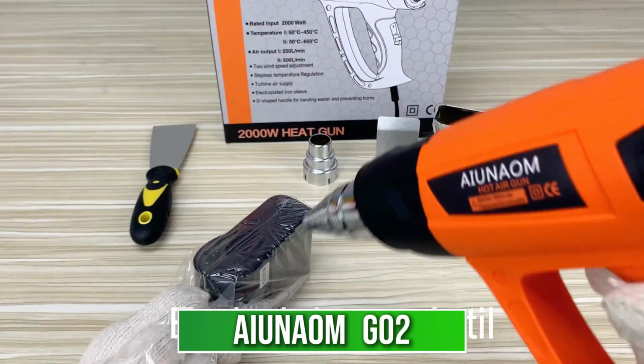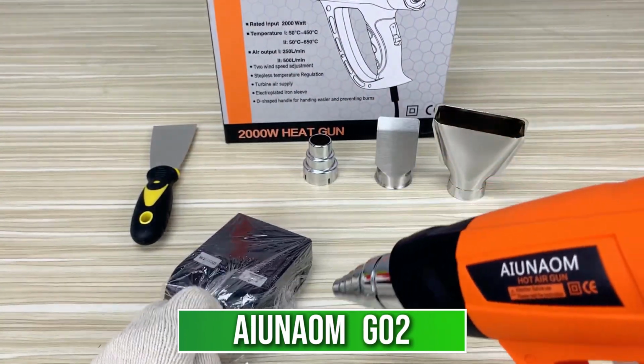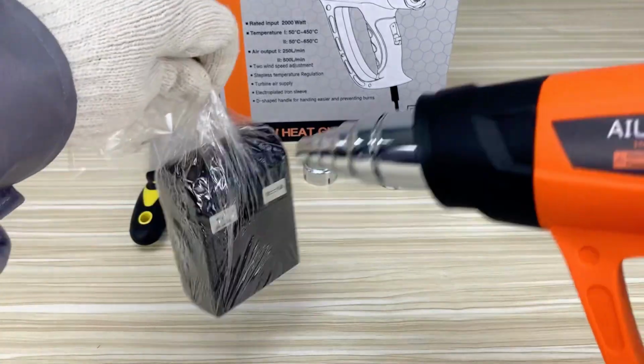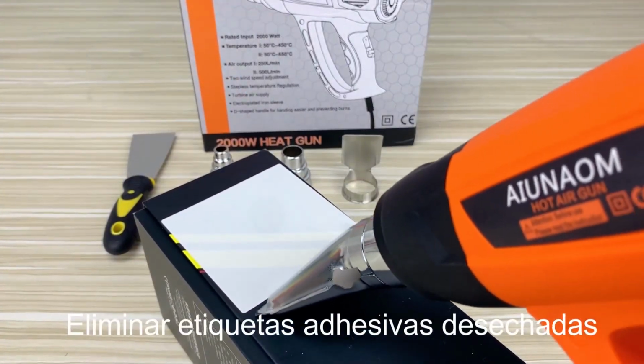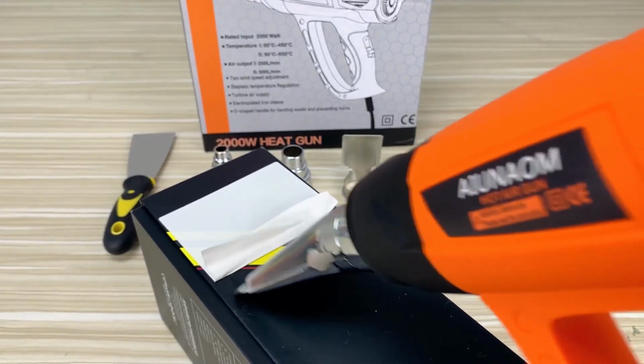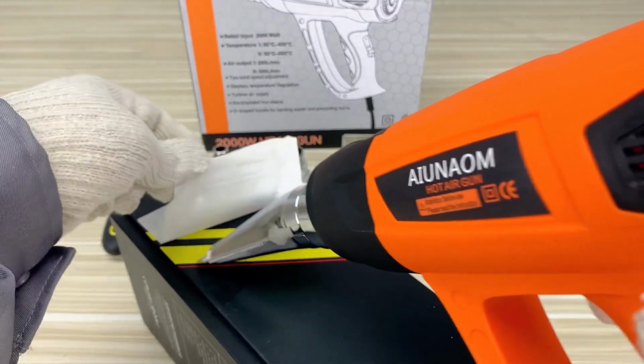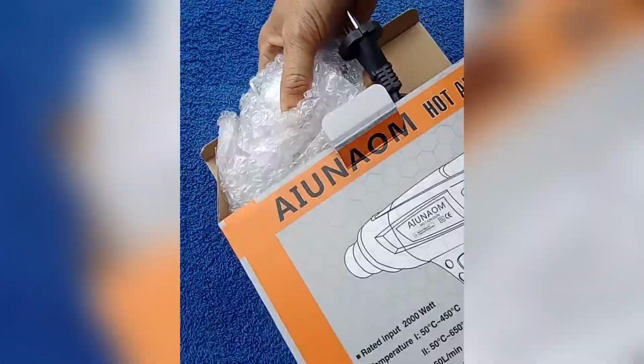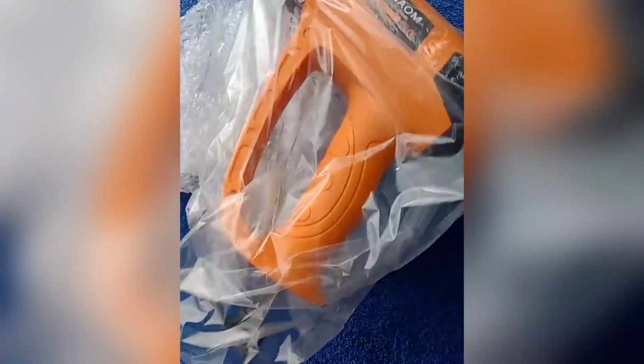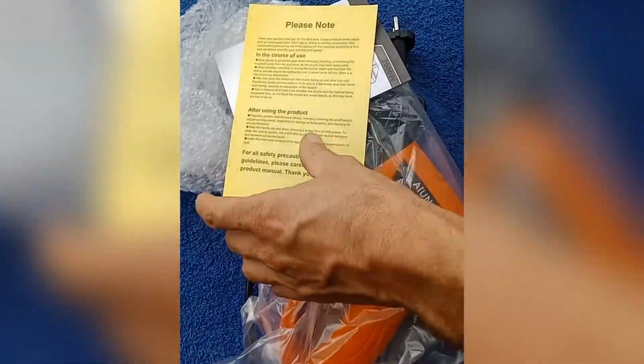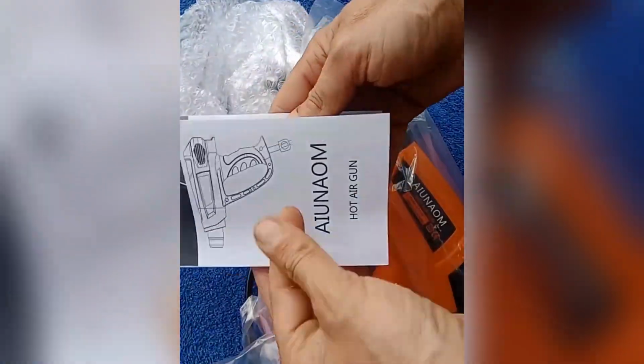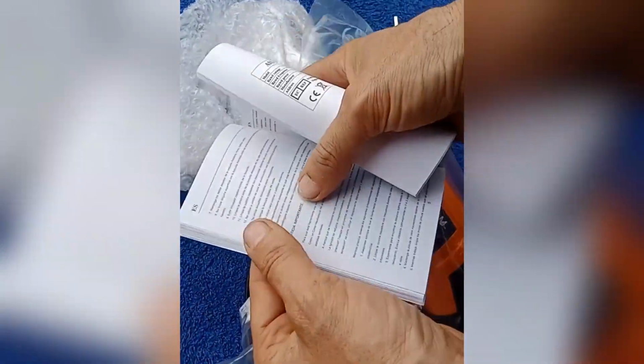For the professional who needs total control, the AIUNAOM G02 is the most advanced gun on this list. 2,000 watts with a range from 50 to 650 degrees, the highest maximum of every model we have covered, and 9 digitally managed temperature levels. This is essential for automotive vinyl wrapping because vinyl films have very specific glass transition temperatures, and going just 20 degrees over means burning a piece of material that can cost a fortune. The 9 levels let you heat at a low temperature first to stretch the film, and then step up to the exact level needed to lock the material memory in place.